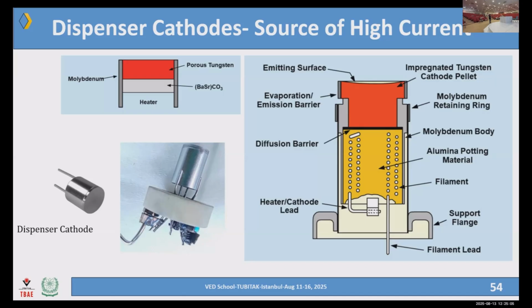But if the surface is contaminated, when I say contamination, it means that the barium layer is polluted, or the surface of the cathode is polluted with some contamination, then you can go to the conditioning cycle again, and the thing is fresh. So remember the point where I mentioned that it should be cost effective, it should be replaceable. If something happens, you should be able to recover it. That's why those modern cathodes are coming with this feature. If something happens, if your system is down, you can recover it in more or less 2 weeks. Yeah, 2 weeks should be enough time to recover it.